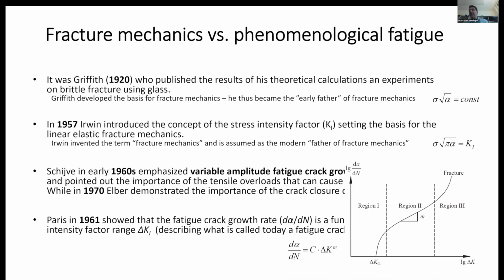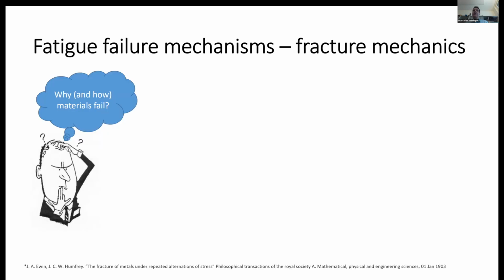And he was the first that suggested this quite famous today FCG curve, the fatigue crack growth curve, where he suggested that this middle region here, region 2, has a continuous slope. It's like a line. And this is what we call today the fatigue crack growth curve.